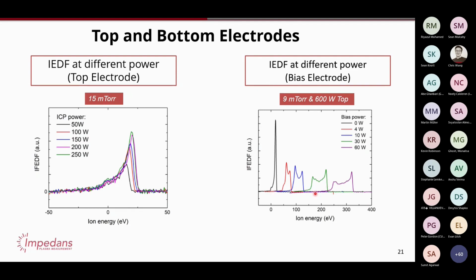So let me put it another way. The 60 watt situation creates this type of plasma with this sort of energy. Maybe it creates the right chemistry for you, the right energies for you. If you then pulse that and change the duty cycle so that now the 60 watts is only on 50% of the time, you're producing the same plasma when it's on, but the average ion energy is decreased. So you can create the correct plasma, but change the ion energies by changing the duty cycle on a pulsed RF system.